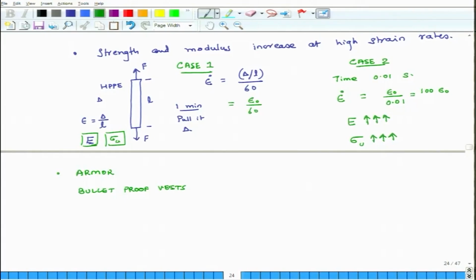So, you use even Kevlar for this type of application. Kevlar also can take a lot of energy, but these guys are very light compared to Kevlar because their density is lighter. So, they are even more efficient. In a bullet impact, when a bullet comes, you have to stop it in a very small time, and in that case the strain rate is very large, because the bullet goes into it at a very fast speed. So, strain rates are extremely high, and the higher the strain rate, the higher its strength and modulus become.